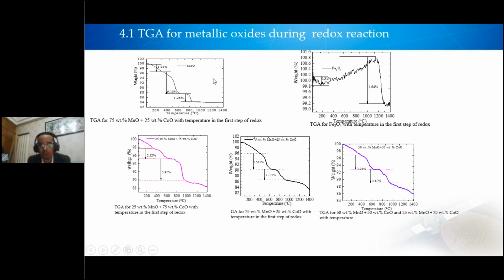Okay, here we see that for the different compositions, for pure manganese oxide we see multi-decomposition here. The 25/75 composition also shows multi-decomposition, and then this is a mixed oxide. So we see that for 25%, 75%, and 50% compositions, in the 50% composition of cobalt, almost the normal situation happened in the thermogravimetric analysis.